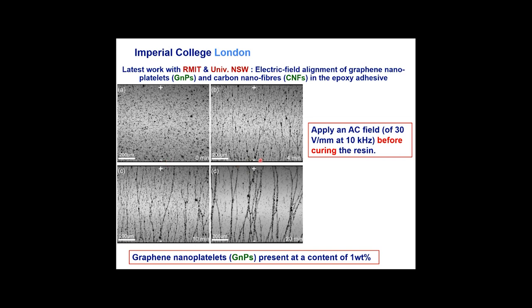And we apply AC field between the two substrates. And as we apply the AC field, you can see that we start getting alignment, in this case, the graphene nanoplatelets. So we actually align the graphene nanoplatelets inside the adhesive layer. Obviously, we do this while the adhesive is liquid before it gels and cures. So we do this early on in the process. And here's the aligned GNPs. You can see we get rather nice chains.